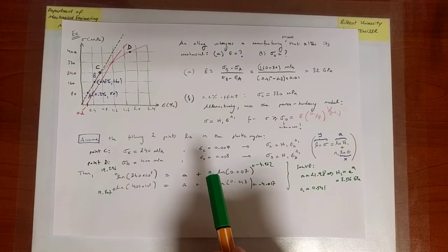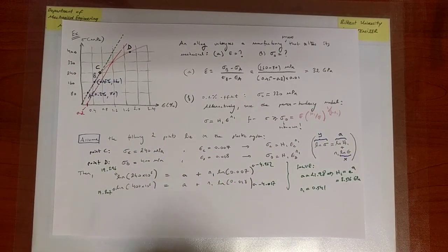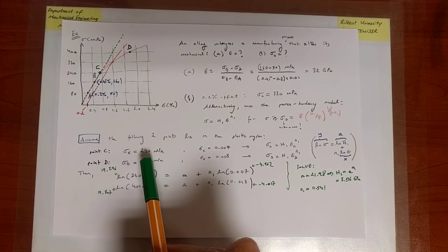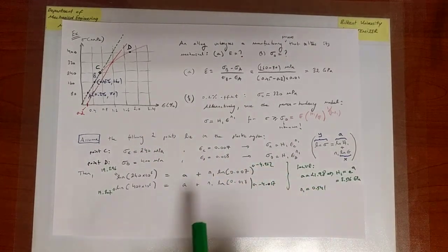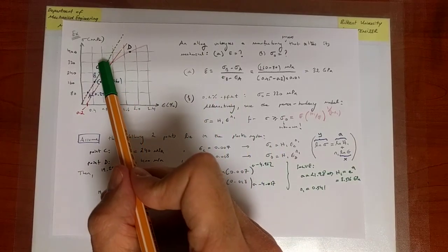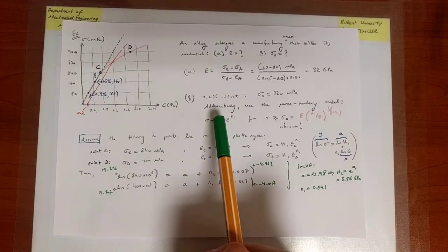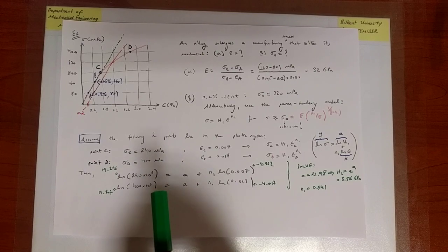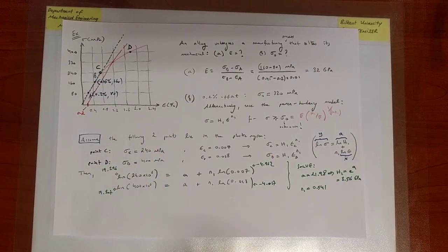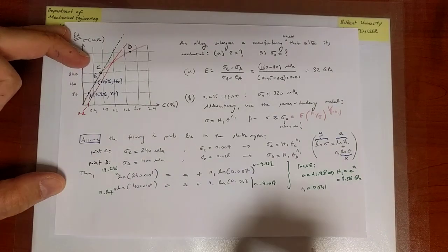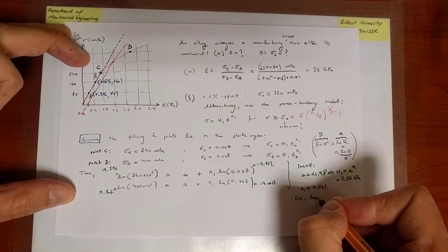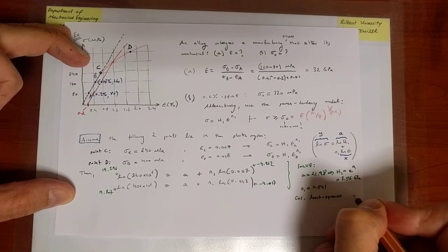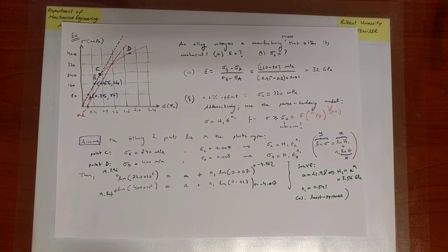A better way to do this is to eliminate the effect of the choice of the points, because if you were to choose 2 other points, you would get 2 entirely different constants. If you choose a lot of points and try to make sure that my model remains as close as possible to all of those points, it's called the least square procedure, and that is a better way to determine free parameters in a model in such a way that the choice of the points does not play a significant role.